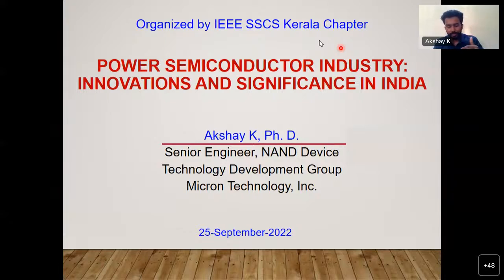So silicon carbide has the potential even beyond 1.2 kV, up to tens of kilovolts. The reason is that when you want to make very high voltage devices, you want to make those devices vertical. Vertical means the current flow will be vertical from top to bottom. In all the slides that I've shown you, you might have noticed that the contacts are on the top and bottom, right? So the current flow is vertical, and that is very crucial in reducing the specific on-resistance. Otherwise, if you make devices lateral, it occupies a lot of chip space. Only when you make vertical devices can you have low specific on-resistance for a given breakdown voltage.